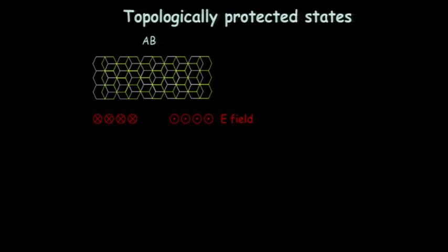And so we can also look at that if you had just Bernal stacked graphene, and instead of applying a constant electric field, you apply an electric field which rotated from out of plane to in plane. There would be band gaps on the left-hand side and the right-hand side because we have an electric field on both sides. And here in the middle, where the electric field is 0, at some point it's going to be 0. And in that point, there would be a conducting, a non-insulating region of the sample.